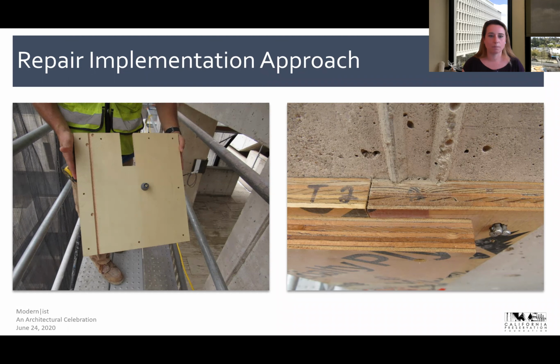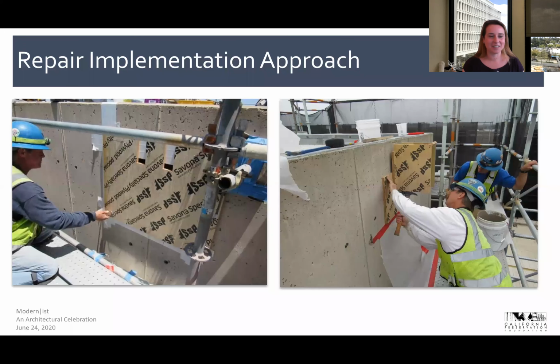against the substrate itself. And you can see that in the photo on the right, just how tight a fit we were able to achieve around these fins due to the high level of craftsmanship of the carpenter. Again, finish carpentry was needed here.